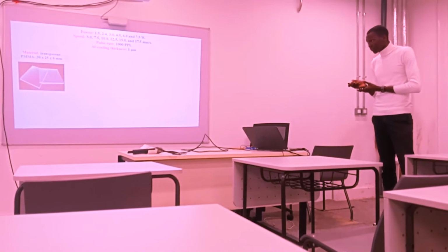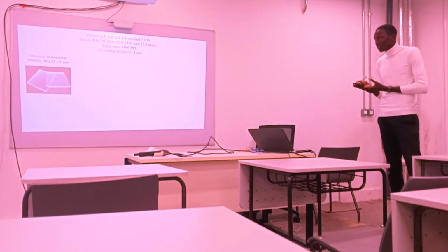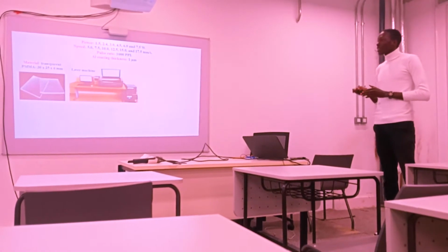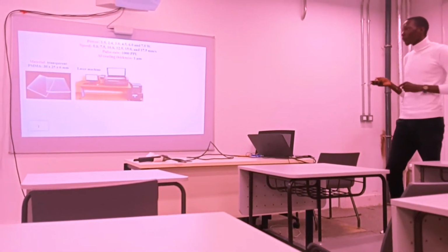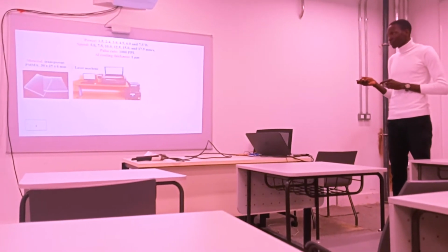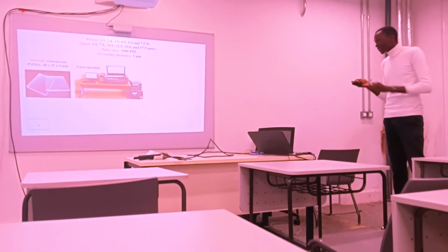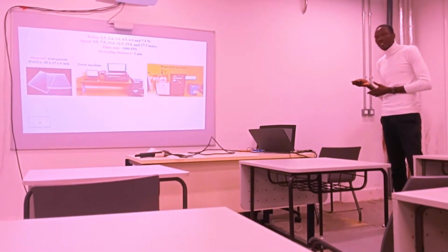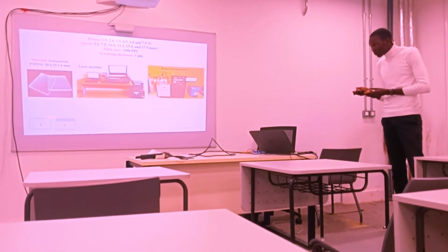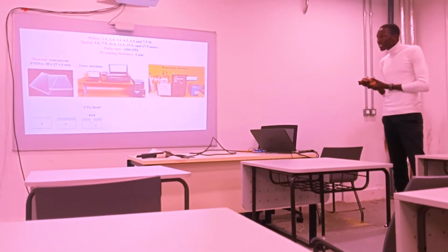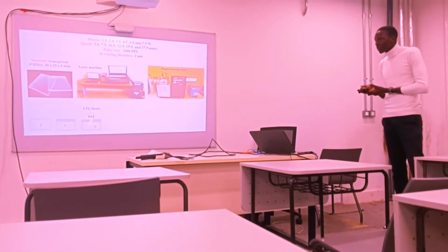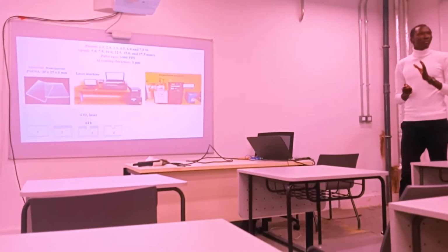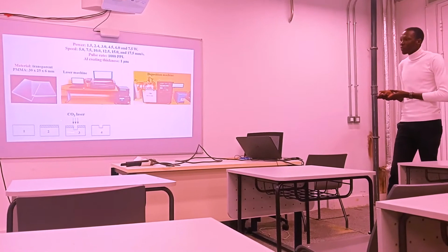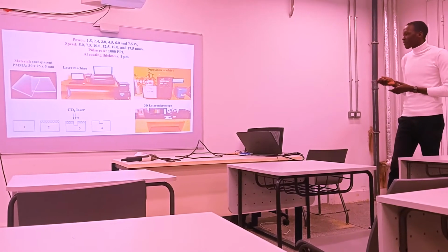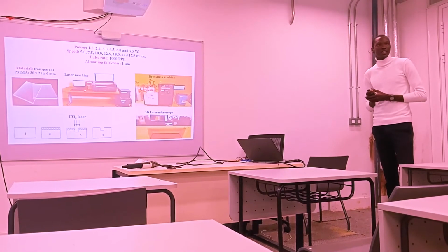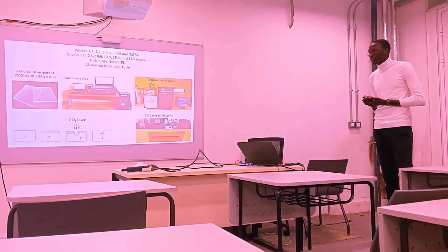This was the work material, measuring 30 by 27 by 6 millimeters, transparent PMMA. And then, using the laser machine, we cut the samples. And then, using the deposition machine, we deposited an aluminum layer on top of the samples. Then, using the laser machine again, we fabricated the microchannels. Then, using aluminum etchant, we removed the aluminum coating. And then, using the 3D laser microscope, we did the characterization of the microchannels.